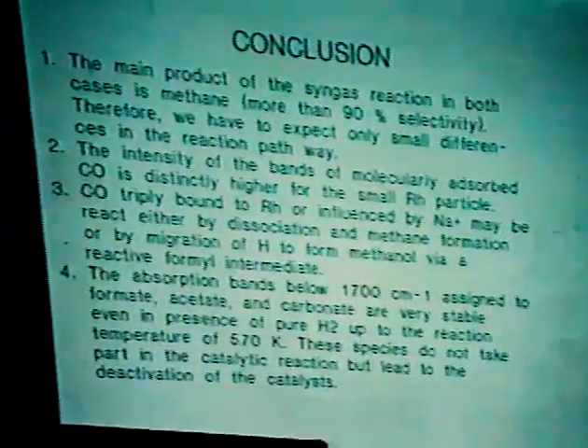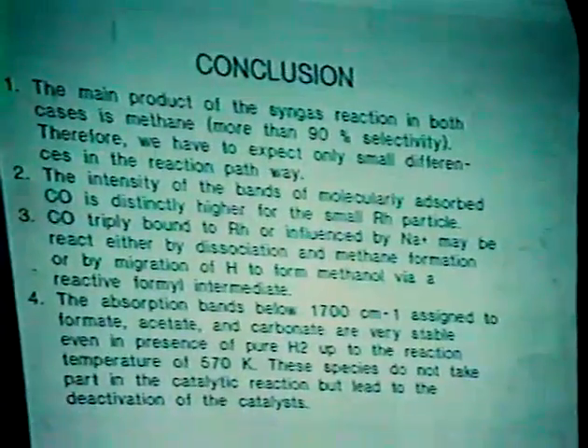Therefore, from this result, we draw a third conclusion: that CO triple-bonded to rhodium or influenced by sodium cations may react either by dissociation on the rhodium particles and methane formation, or by migration of hydrogen to form methanol via a reactive formyl intermediate.